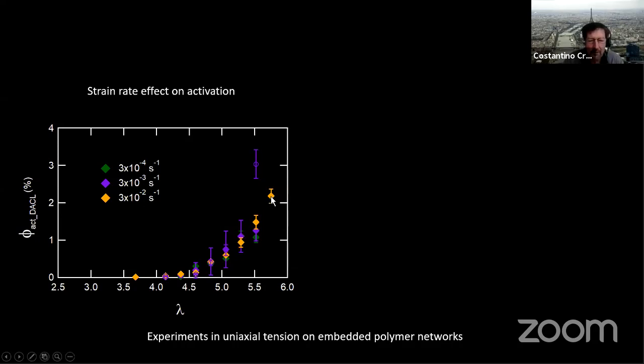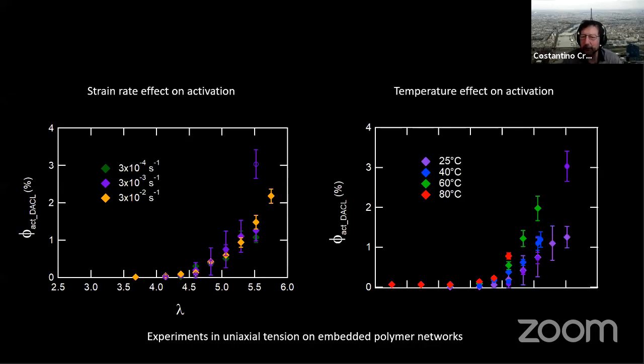So the low strain rate is green, intermediate is purple, and here the orange is the fast strain rate. Now this point has something different. I think it's a different experiment, but roughly we don't see within these two decades a lot of difference in the strain rate in terms of probability of breaking. When we did the experiment as a function of temperature, it's not quite true.